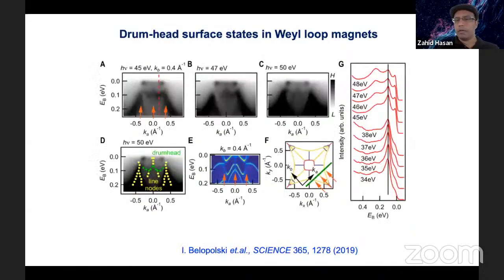But having those Weyl loops doesn't necessarily tell you it's topological, at least from my point of view in an experimental sense. We have to find the bulk boundary correspondence. In other words, do the Weyl points connect to create a drumhead state? Are there states that are non-dispersive in the kz direction? That's what we test by changing photon energy. It's the same sample, and the only thing we change is the photon energy, and we see that these states do not disperse, meaning that they are kz independent. So these states in momentum space connect those Weyl lines, which is what is expected in a topological system. Those Weyl points would be connected by states like Fermi arcs, a generalization of the Fermi arc. So that is how we can track the drumhead states.